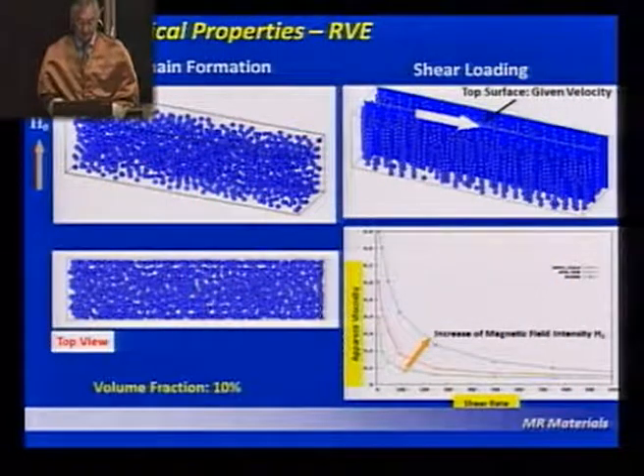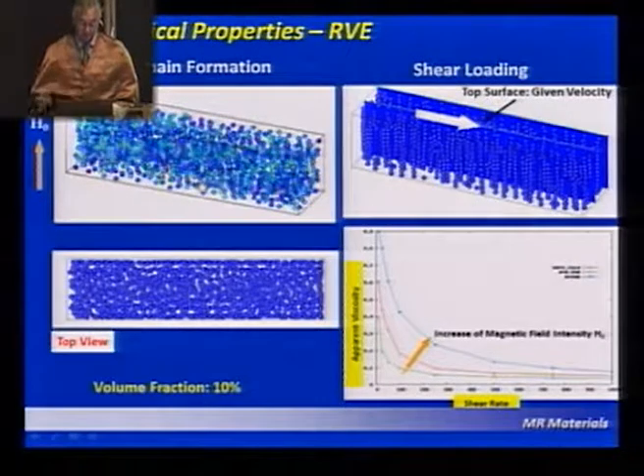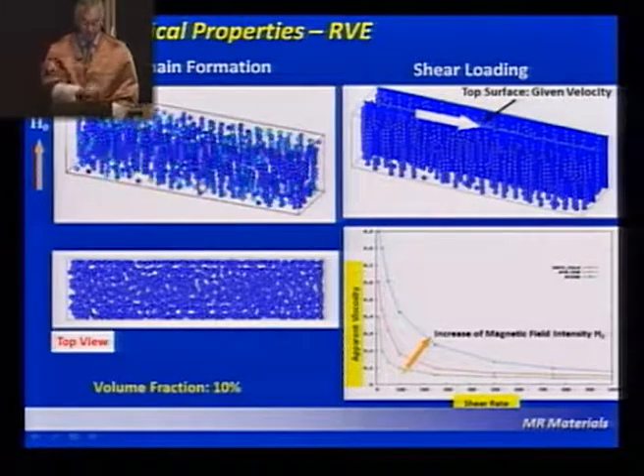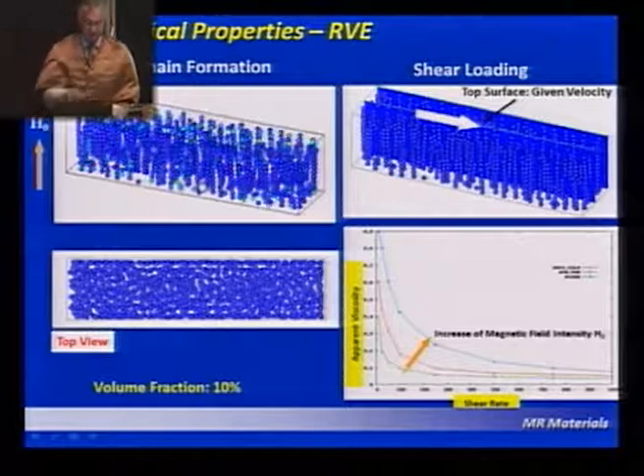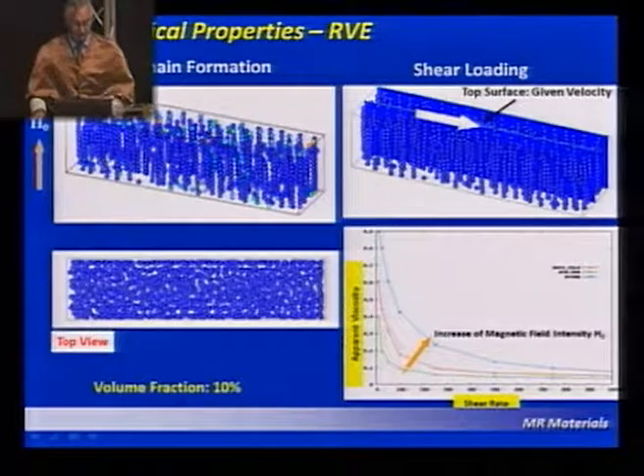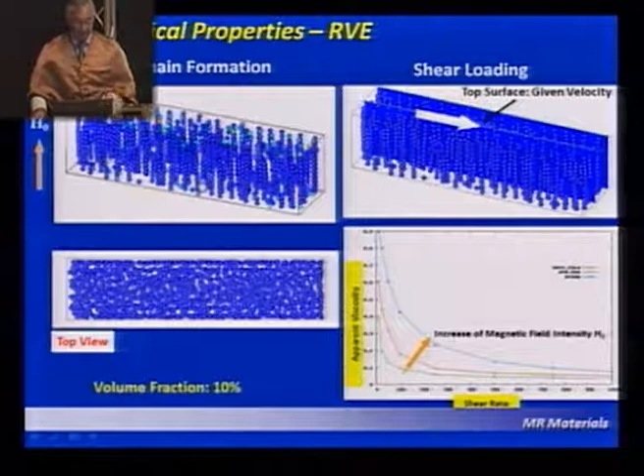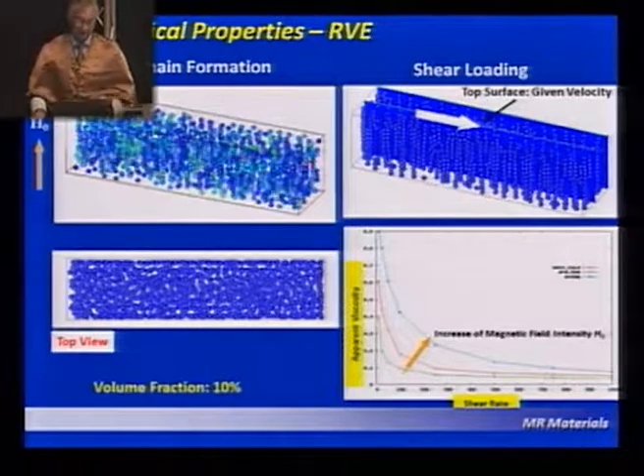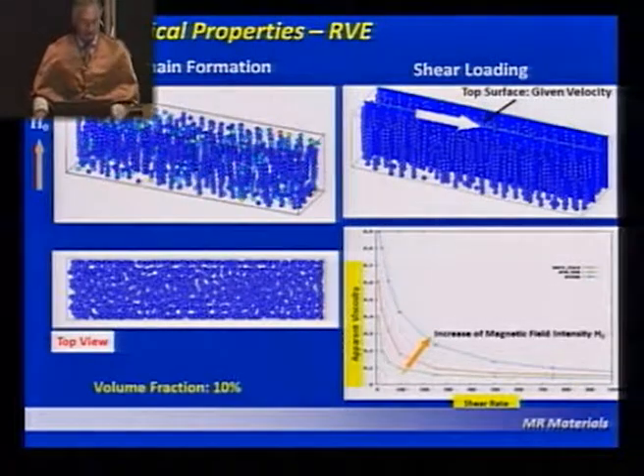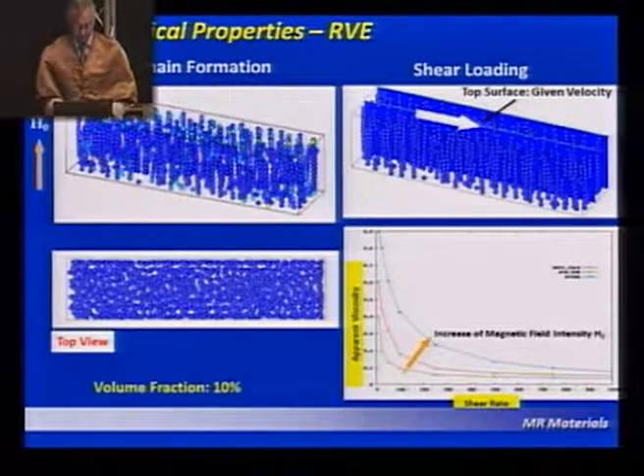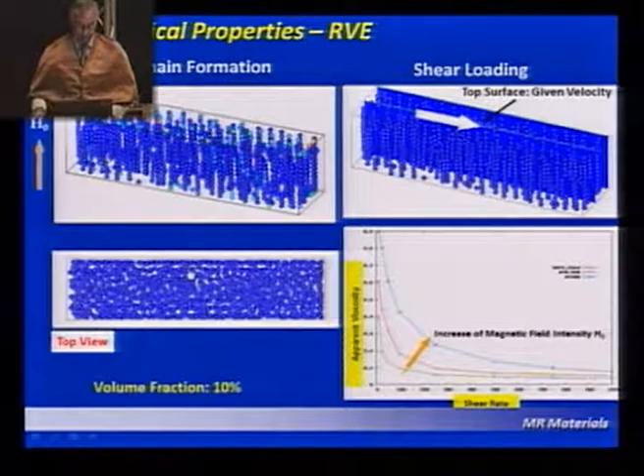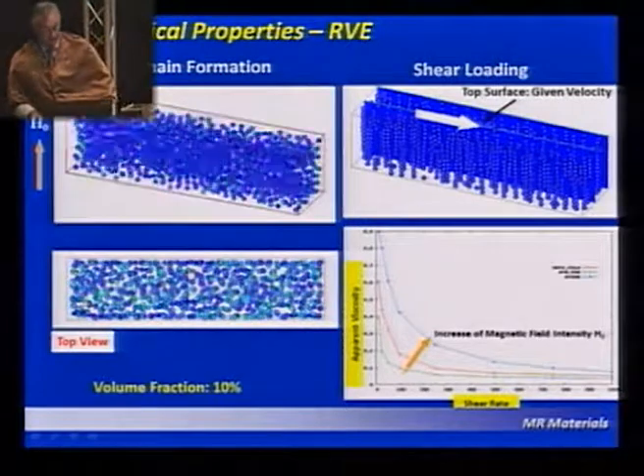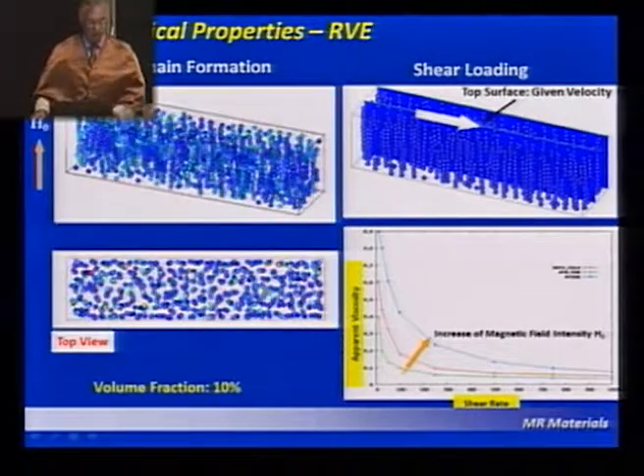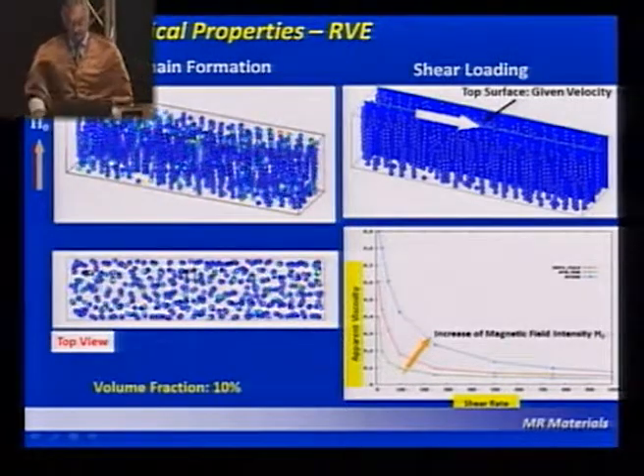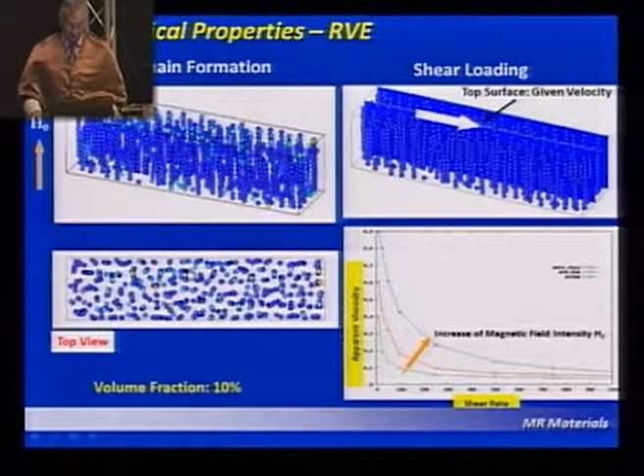So if we take an RVE of that, what we have here is randomly distributed particles subjected to a vertical magnetic field. And what you find is that just by applying the magnetic field, the particles arrange themselves into chains. And this one is just looking at the top of the same thing. So the next question is, having formed these chains, how do they actually change the viscosity of the material?